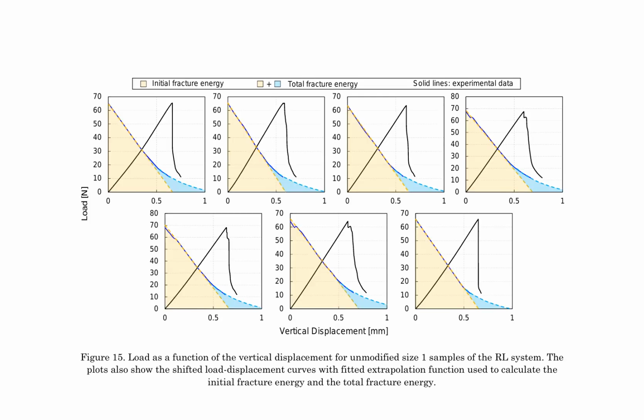Mechanical testing was conducted on unmodified samples of the RL system to examine load displacement behavior and calculate fracture energy. The results, presented in figures 15 and 16, display the load as a function of vertical displacement for size 1 and size 2 samples, respectively. The load displacement curves for size 1 samples, shown in figure 15, exhibit a characteristic shape that allows for the calculation of initial fracture energy and total fracture energy using a fitted extrapolation function. The initial fracture energy is determined by extrapolating the load displacement curve to the point of initial crack propagation, while the total fracture energy is calculated as the area under the entire load displacement curve.